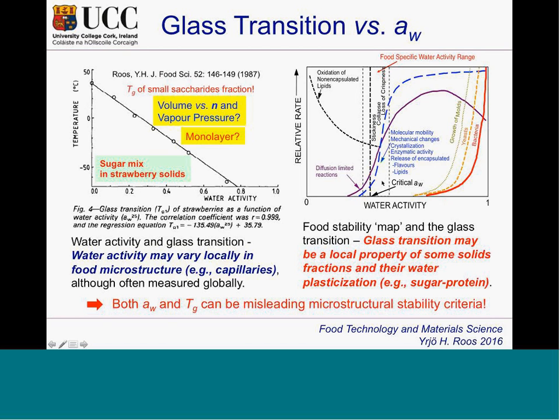and that would be quite low for these strawberry solids, but it varies with the molecular weight as shown in previous diagrams. But that would also explain that there's stickiness, collapse, loss of crispness, other things happening soon after exceeding that critical water activity if the temperature were constant. So the diffusion limited reactions also go up, and there's a number of studies on that.